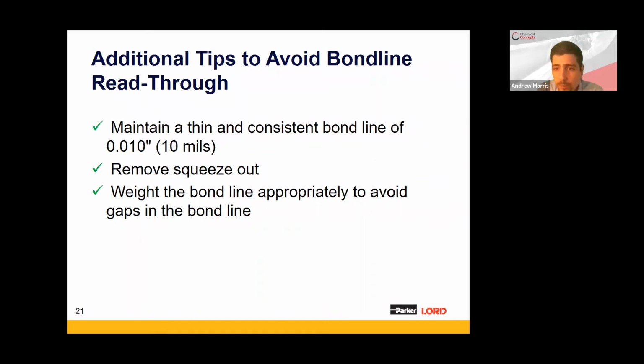Another important consideration for reducing read-through and maximizing performance is to create a consistent bondline thickness throughout your joint. So you want to make sure that whatever weight or pressure you're using is applied evenly. If you're using weights, you want to make sure that a similar weight is used on one side of the panel versus another. You wouldn't want to use a 20-pound weight on one side and a 10-pound weight on the other. You want to make sure that pressure is applied consistently across the part.